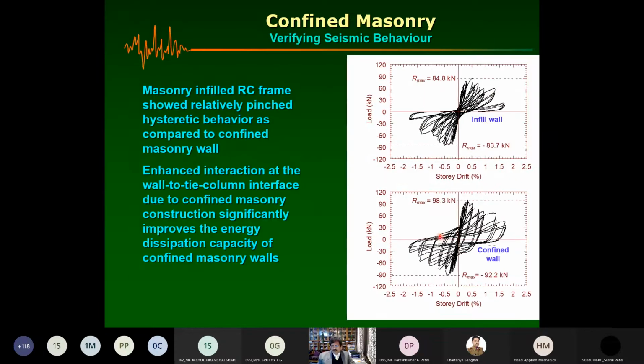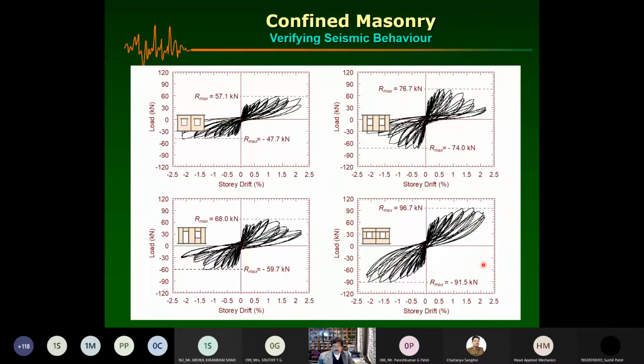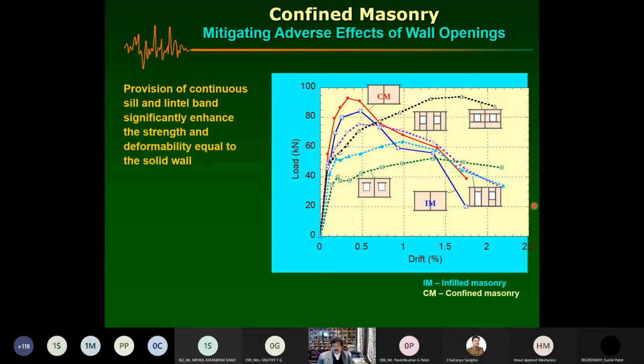If you see here, this is the solid wall. So what it means is that even with the presence of this opening, if they're well confined as in our system, we do not lose any peak strength, despite having an opening. And these continuous horizontal bands are better than the vertical tie columns. Okay, so this is another comparison.